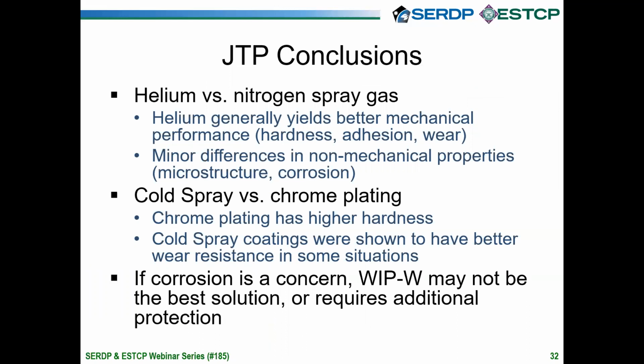So to conclude the joint test protocol results, there's a few main takeaways we can make. First, for helium versus nitrogen spray gas, helium generally yields better mechanical performance and minor differences in non-mechanical performance. But we saw that the difference between helium and nitrogen was minor compared to the differences between feedstocks. So likely for these type of applications, you should be able to get away using nitrogen gas, which is much cheaper than helium gas, by choosing an appropriate feedstock material.